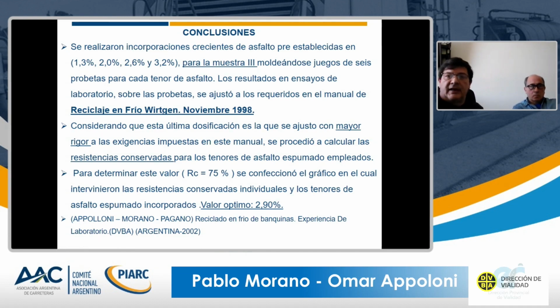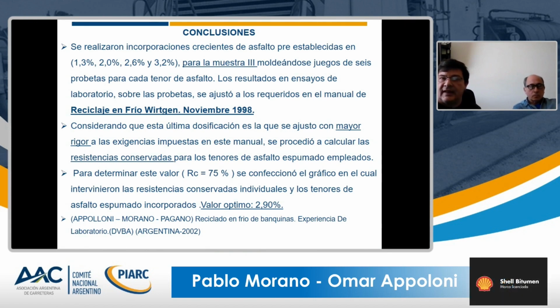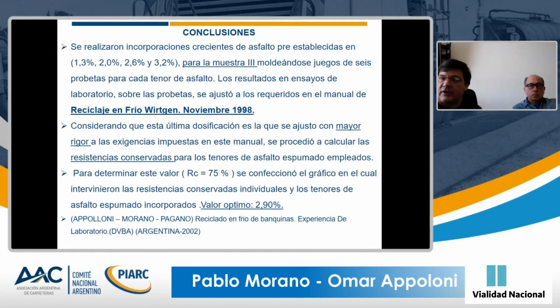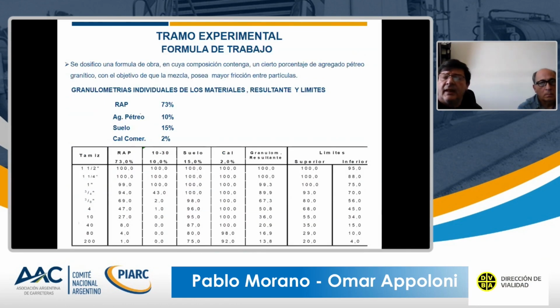In the first stage, that was the lab stage, we can get to the following conclusions. We incorporated more asphalt from 1.3 to 3.2 in sample number 3, and we molded cores with each percentage of asphalt to do all the tests that we wanted to conduct in the lab. We also took into account the maintain resilience to know what type of asphalt we needed to use. So in this case, the optimum percentage of asphalt to use was 2.9%. That was our conclusion. That was the first stage, which was the lab stage.